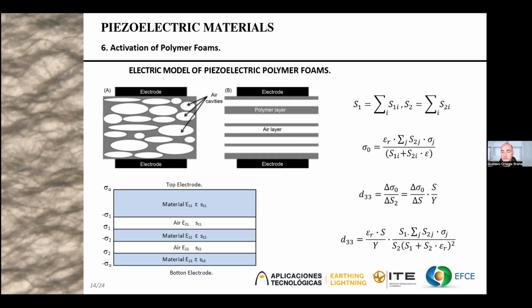The quantity of charge on the electrode depends on the variation of the thickness of the material when a force is applied on it. Also, it is a function of the permittivity of the polymer, but the only part that moves in this material is the air, because the polymer is incompressible. So the d33 charge per newton of force will be the charge density sigma that we see in this equation, divided by the Young modulus, resulting in the d33 equation, which is the response of the piezoelectric material in picocoulombs per newton.